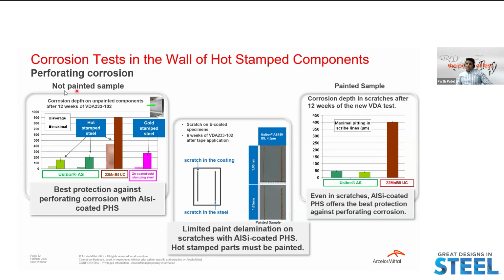If you paint the samples - this was an unpainted sample, as stamped, you stamp it and just do the test. But if you actually do testing on painted samples, your depth of pitting corrosion is less than 50 microns, which is much less compared to other products in the market. So the message here, again, the myth is that AlSi is not better than GA coating - that's a myth. For perforation corrosion it's much better than GA coated. Yes, for cosmetic corrosion it's a different issue, but for perforation corrosion, this is one of the best in class in the market today.